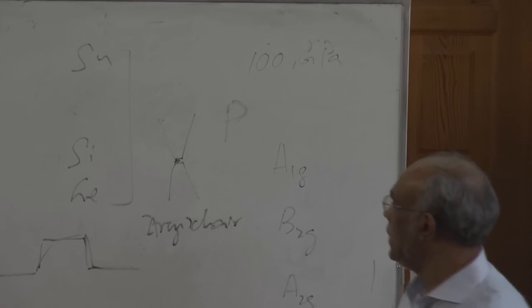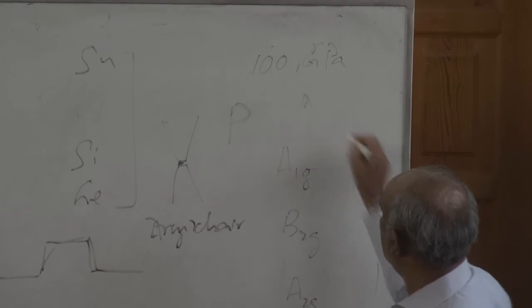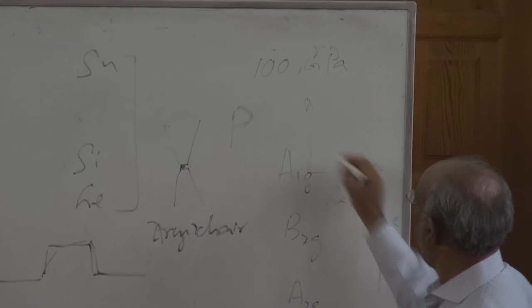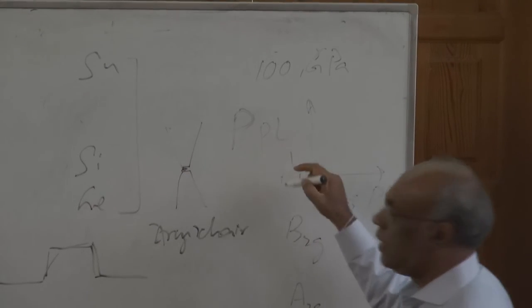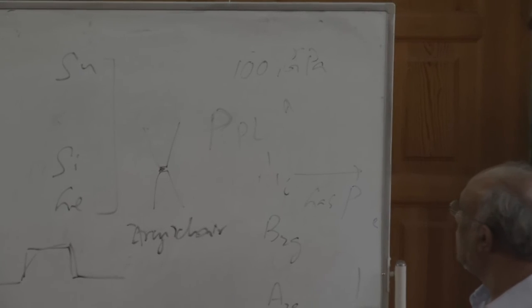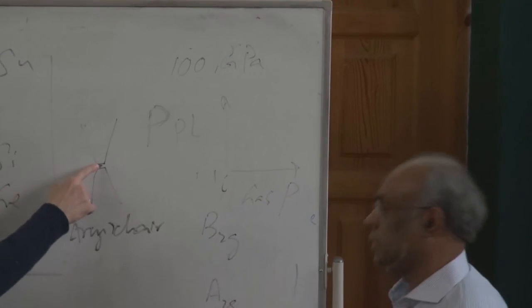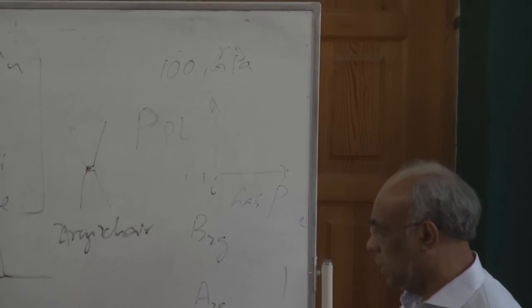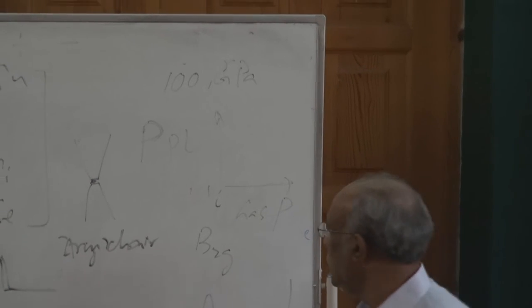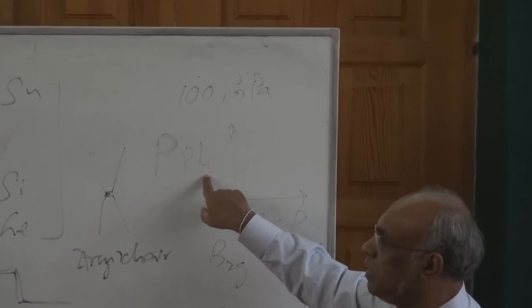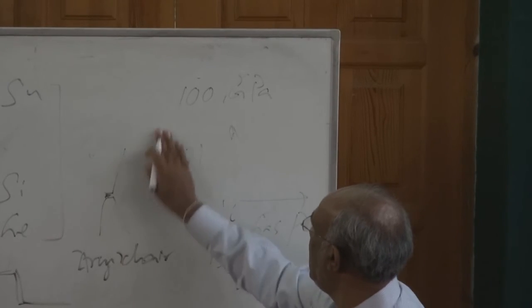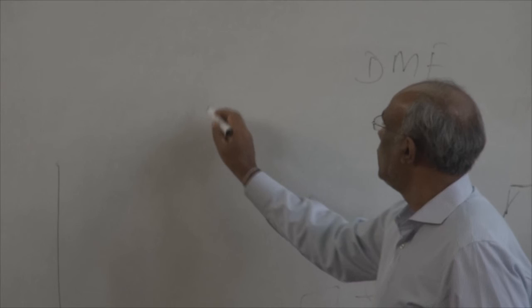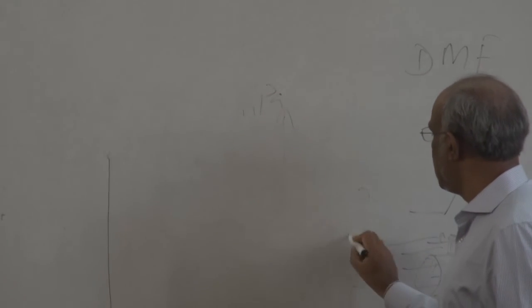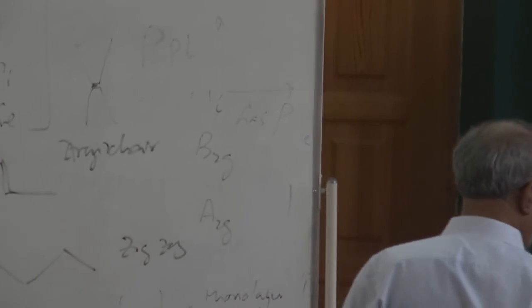First you do it with your gas pressure and your PL shift. The first time you put the ruby in, then you calibrate it. Then we know this gas pressure and the PL, and then we know PL and the real pressure. So you have the GPa pressure versus the PL, and from that you can get the real pressure.